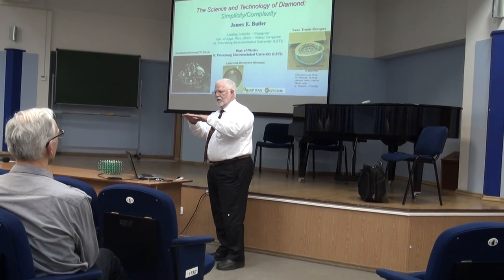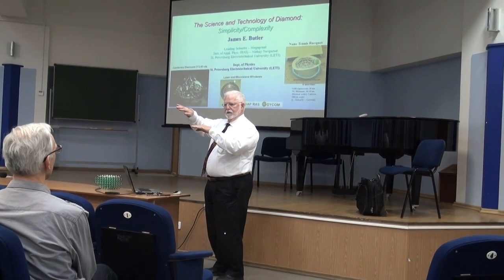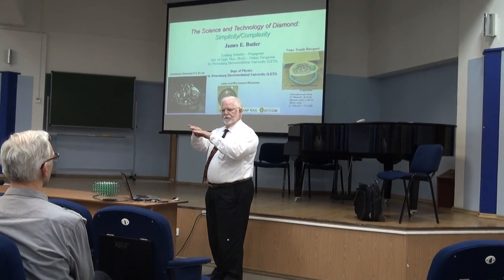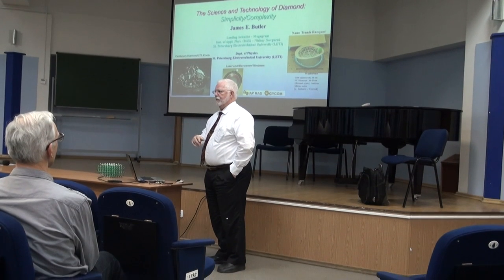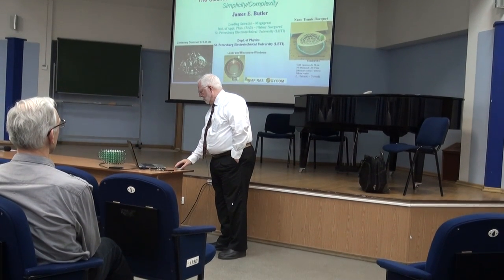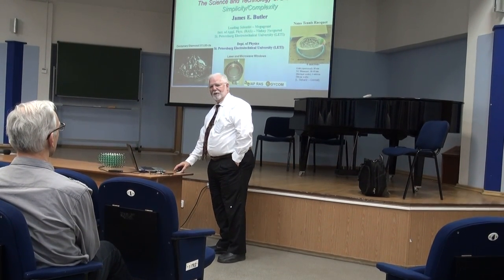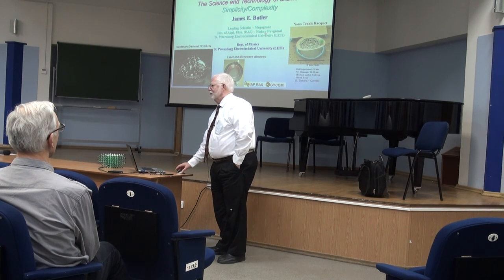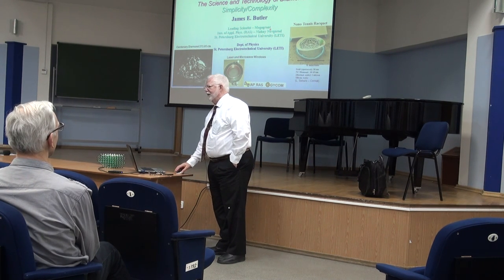And the gold caused stress, so the resonator bent. And of the thousands that we made on one wafer, one of them just happened to have a dust particle there. So that's why I like this picture. I call this my nano tennis racket.